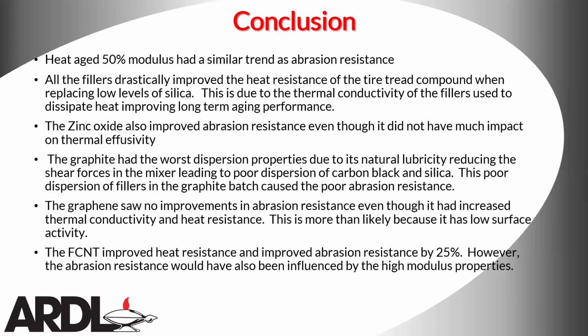So the functionalized carbon nanotube improved heat resistance and improved abrasion resistance by 25%. However, the abrasion resistance would have also been influenced by the high modulus properties. Do you remember at one of the beginning slides when we first started looking at data that 50% modulus was almost double what the control was by adding, I think it's a little bit under 2% carbon nanotubes? So that is also influencing the properties. And that's a good thing because what that means is you could probably use less of that functionalized carbon nanotube.